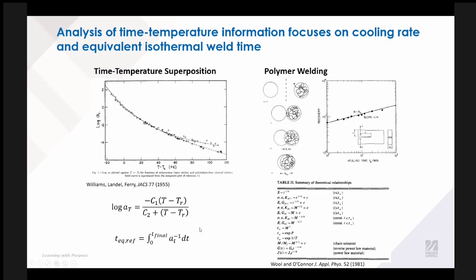The reason it's nice to have a single time at a reference temperature is twofold. One is that it's nice to have just a single quantity to work with. Another is that we can take advantage of polymer weld theory, which is very established and has a lot of scaling relationships for things like modulus or G1C, your fracture energy release rate, which is proportional to time to the 1/2, and things like your strain or your K1C, which are proportional to time to the 1/4. But that's only for isothermal time. So now we have this isothermal time that we can start to scale our predicted strengths to.